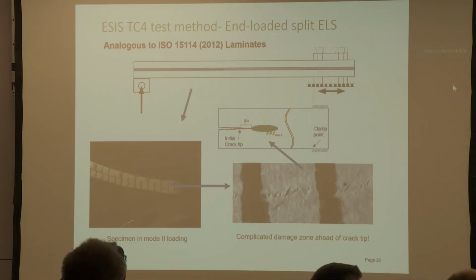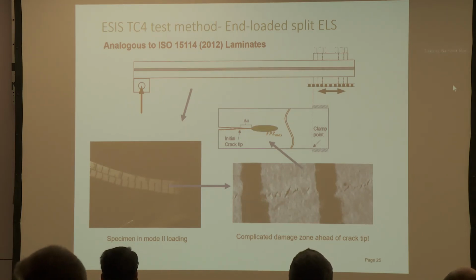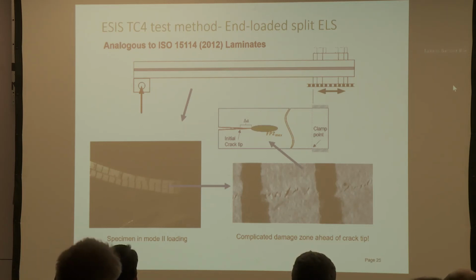In addition to plasticity, for example, one can also see a micro-cracked region, depending upon the precise details of the adhesive, the balance between the toughness and the ductility. This obviously poses a number of challenges, one of which is a fundamental challenge to say, is this genuinely Mode 2 fracture? So Kevin O'Brien from NASA Langley wrote a very nice article many years ago saying, is this process shear failure or shear myth? And he was referring there specifically to composites, but of course the same can be argued for adhesive joints.